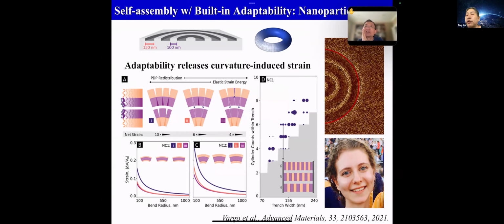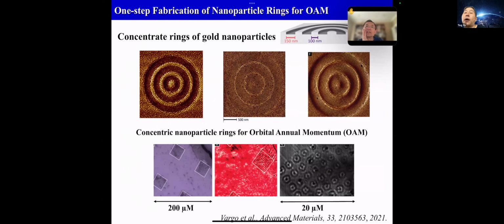So we use a lithography pattern surface. The pattern has large rings, right? So the rings, the trench is 150 nanometers, 200 nanometers, 500 nanometers. And then we put the polymer in there, and the polymer has a periodicity of maybe tens of nanometers, and the polymer inside has a nanoparticle. So the nanoparticle, the plasmonic peak, gives you this optical effect.